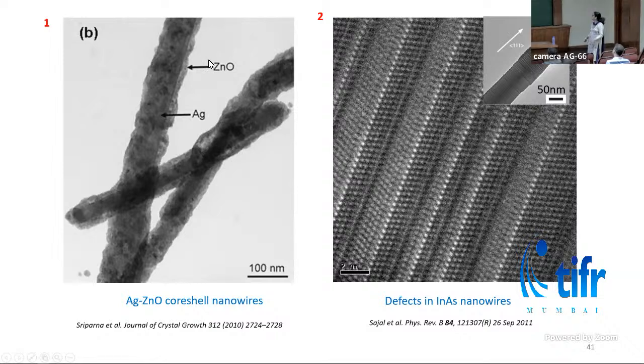In case of TEM, the image is formed by the transmitted beam. That is why TEM is an excellent tool to investigate core-shell structure. So these are silver-zinc oxide core-shell nanowires, where we can see the center portion is silver, which is 50 nanometers thick, and it has a thin layer of zinc oxide coating on it.